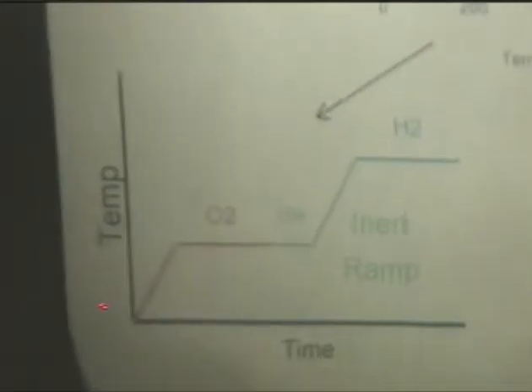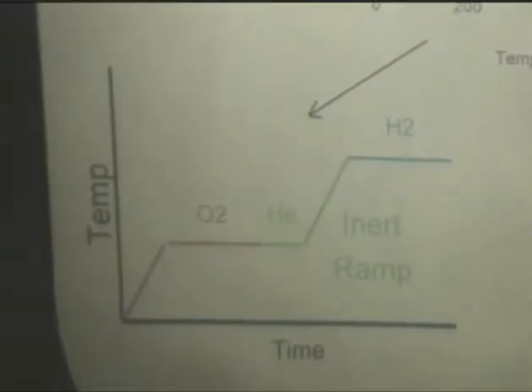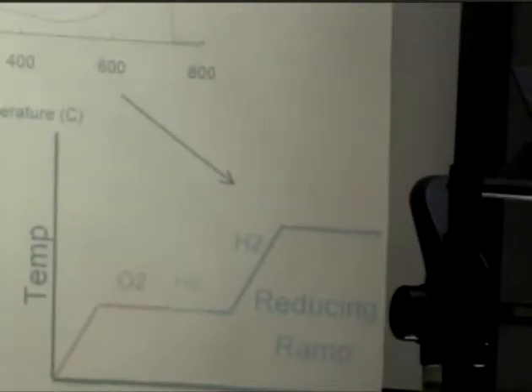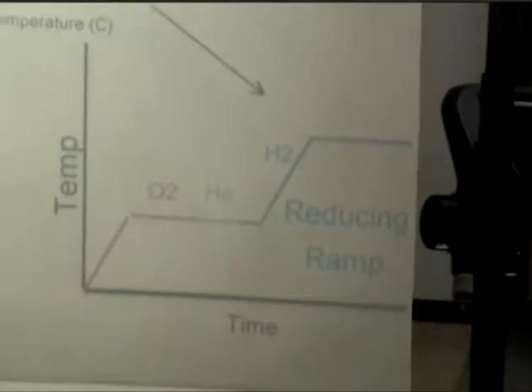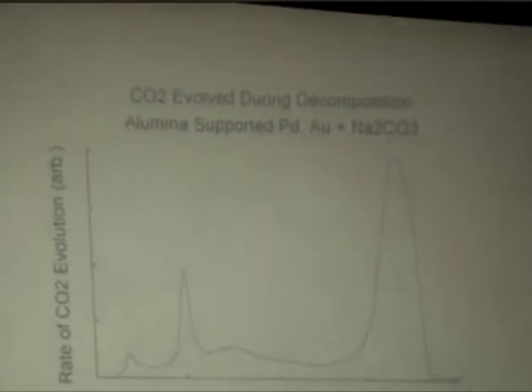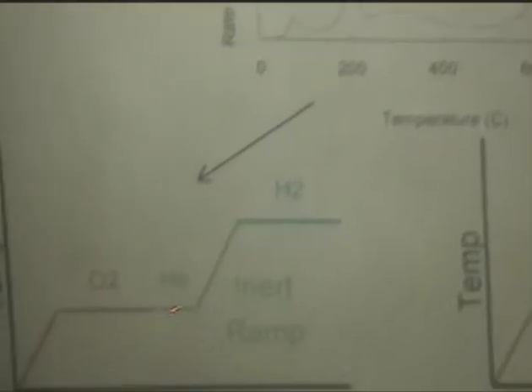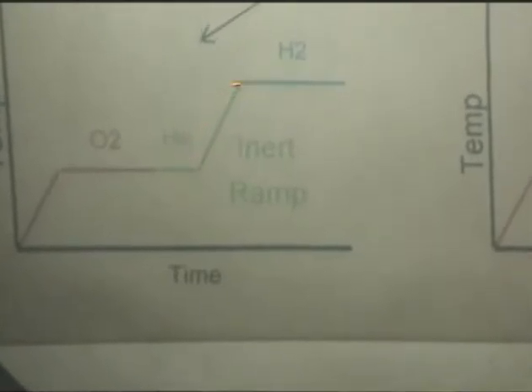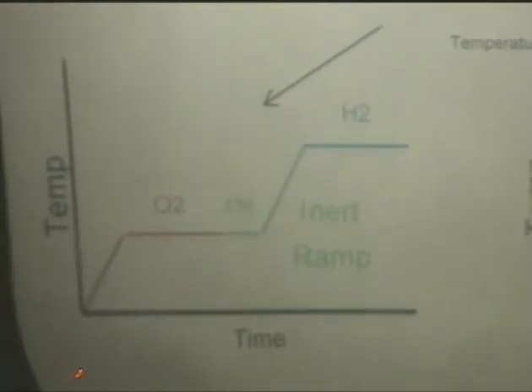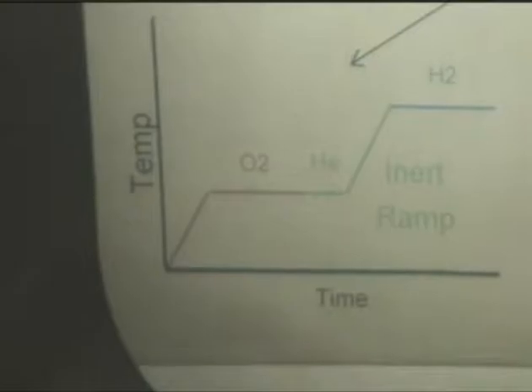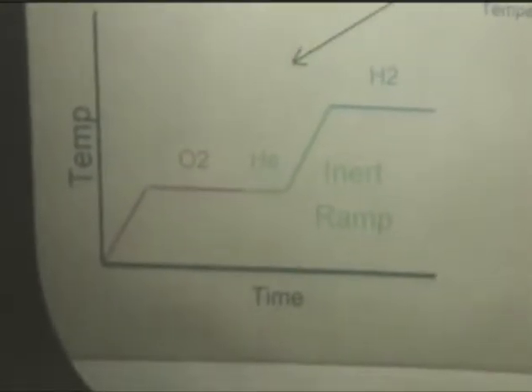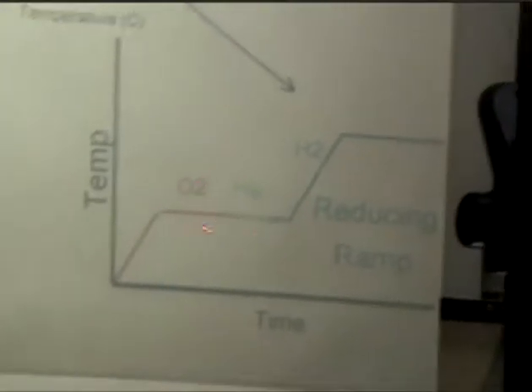And so what we did is we thought, well, simple-mindedly, what happens if we first decompose an oxygen, as is the common practice, and then as we sweep the reactor with helium in order to not get an explosion, we can do that in two different ways. One is that we can sweep the reaction and then ramp the temperature in that inert, and therefore we are effectively ramping that catalyst in its oxidized form. Or we could sweep at the temperature where we oxidize and then ramp as we are reducing.